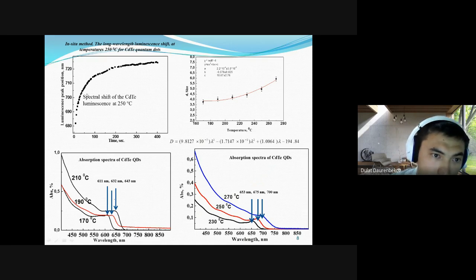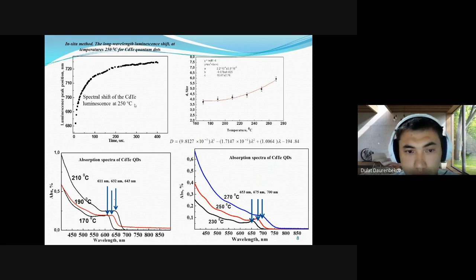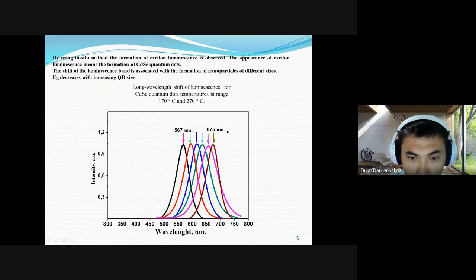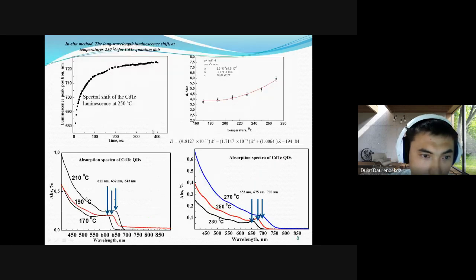Here are exactly the in situ measurements. Each dot is a measurement, and you can set different times, for example each 10 seconds, each 20 seconds or 1 minute. After 1 minute, it measures the position of the luminescence. It's like this, but there's a final result. But here you can see how it starts from the 0 second point and how it goes.